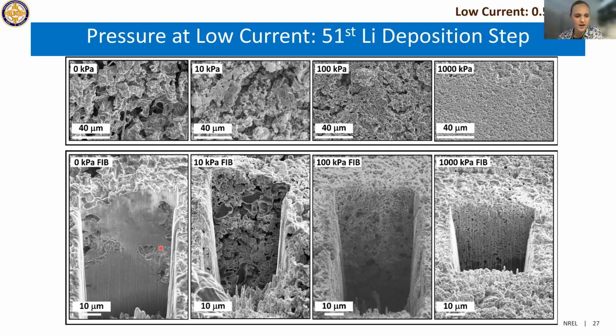Under higher pressure, you could see that there were some nice big lithium grains in here, but there was a lot of reacted material that was SEI components. At 100 kPa, again, it was really hard to see large lithium deposits. There's some lower down, but because of all the cycling, these electrodes get very thick. It was getting to a point where we couldn't use the gallium FIB to mill through the electrode to get all the way down to the current collector, and so we couldn't measure how thick the electrode was after cycling. And then at 1000 kPa, again, there's some lithium metal down here, but a lot of this is material reacted with the electrolyte to form SEI.